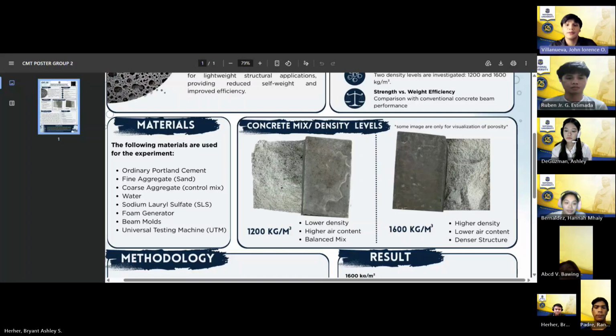Thank you, Ms. Bernaldez. Moving on to our concrete mix and density levels. For our experiment, we investigate two distinct target density levels, 1,200 and 1,600 kilograms per cubic meter. As shown on the poster, these represent completely different internal structures. The 1,200 kilogram per cubic meter mix represents the lower density level. It features a higher air content, creating a highly porous and lightweight structure. However, this high porosity resulted in a lower and less consistent flexural performance, testing between 6.17 and